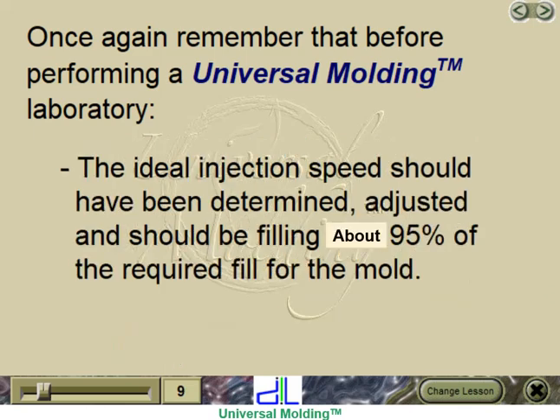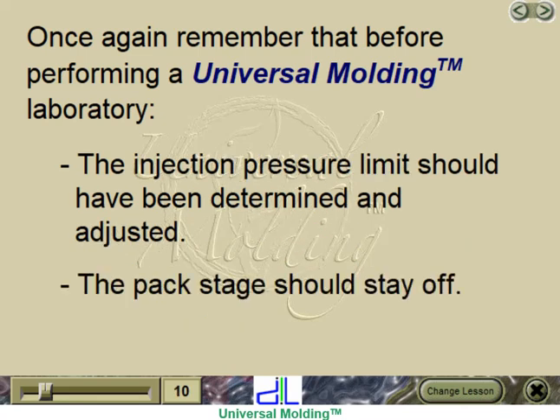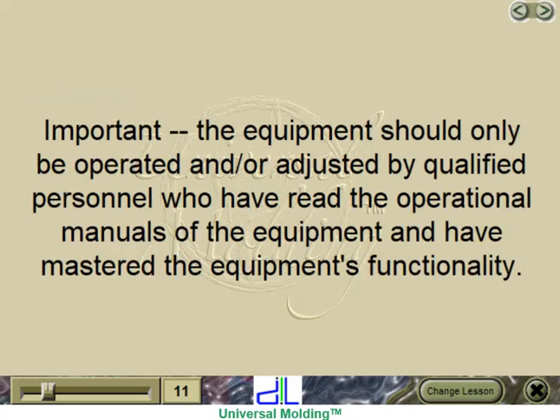The ideal injection speed should have been determined, adjusted, and should be filling about 95% of the required fill for the mold. The injection pressure limit should have been determined and adjusted. The pack stage should stay off. Important: the equipment should only be operated and/or adjusted by qualified personnel who have read the operational manuals of the equipment and have mastered the equipment's functionality.